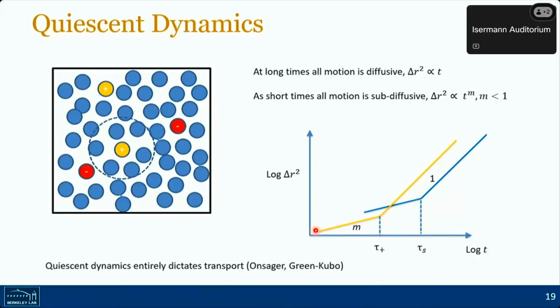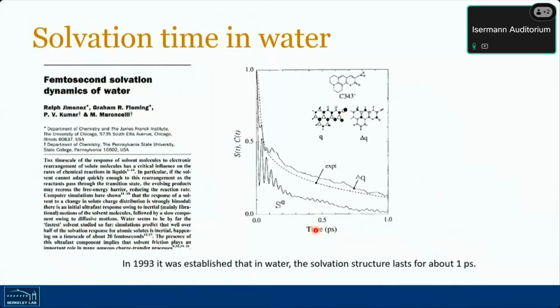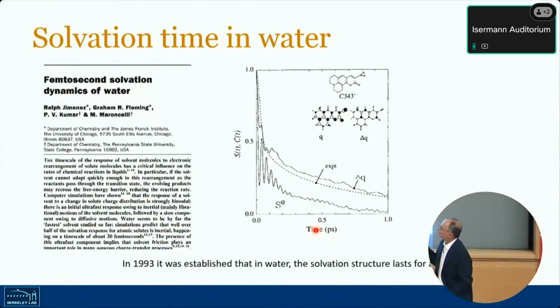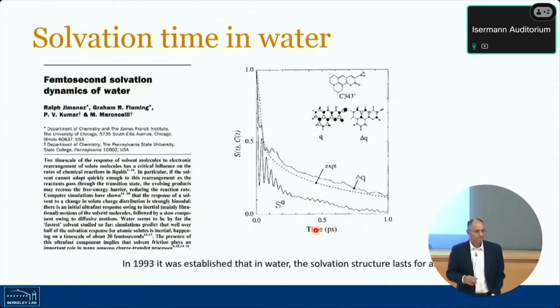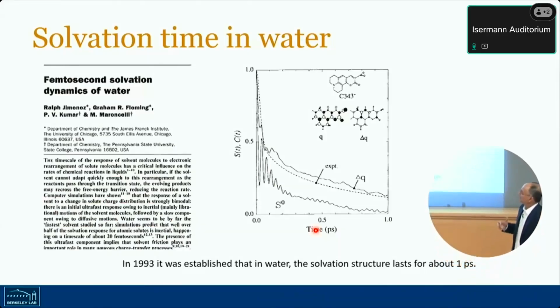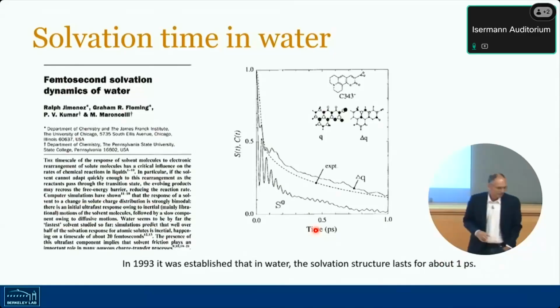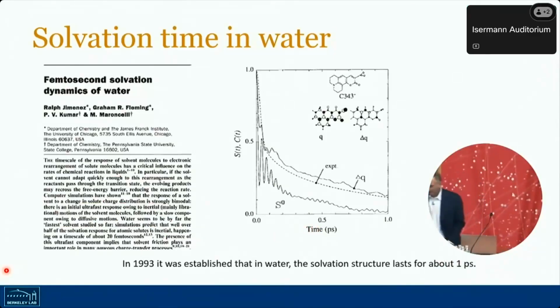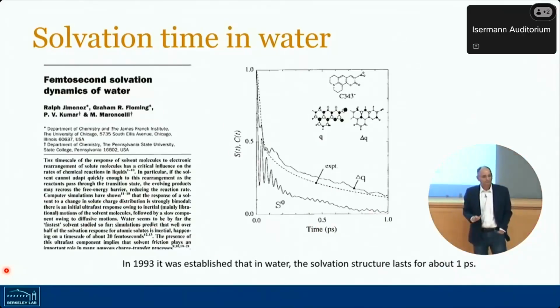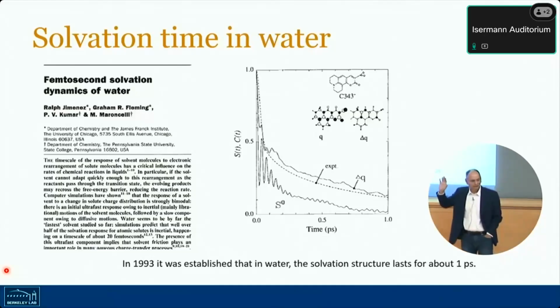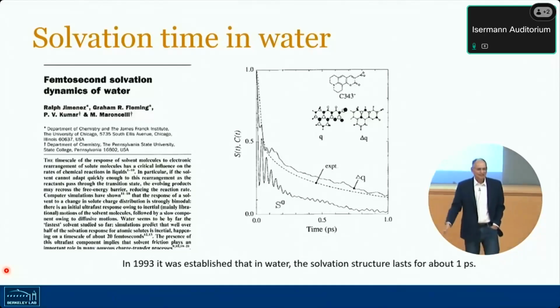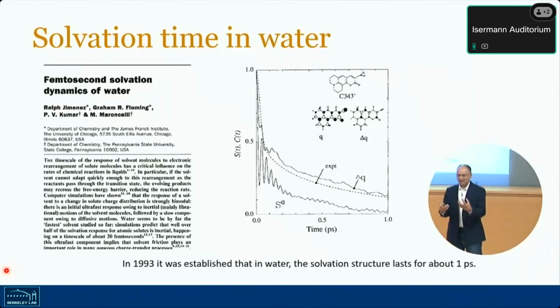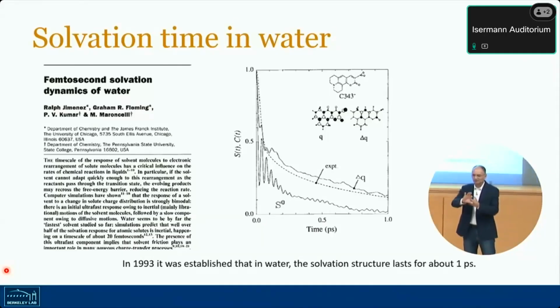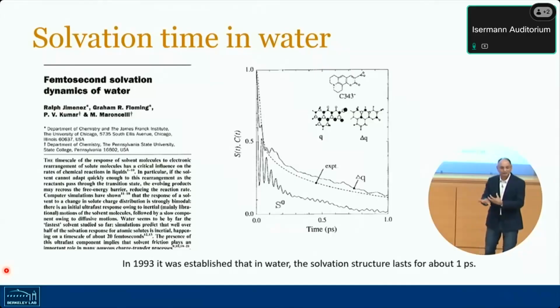Okay. This question was answered extremely elegantly by this group at University of Chicago and Penn State in the context of water. And this beautiful paper showed that, in fact, when you have water surrounding ions, it lasts for about a picosecond. Okay. And this is some fancy 2D IR spectroscopy with some strange molecules, because that's what they needed. But subsequent work has shown that when you go to water, it's roughly a picosecond. Okay, so you can imagine have ion, maybe sodium, and the water molecules are in a well-defined configuration for a little while, and that little while is 1 picosecond.